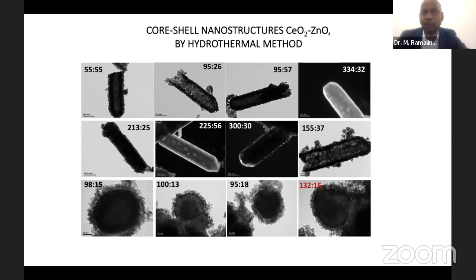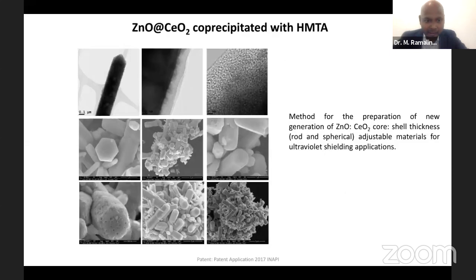Of course, many people play with zinc oxide. Zinc oxide is easy to make different kinds of morphology. You can see how uniform, differently sized materials of cerium oxide are deposited over the zinc oxide. In the top second image, you can easily see the thickness, how it is really attached to the zinc oxide cores.